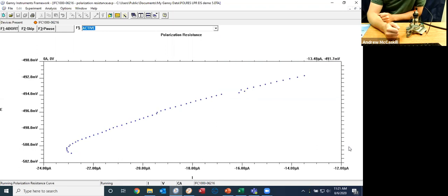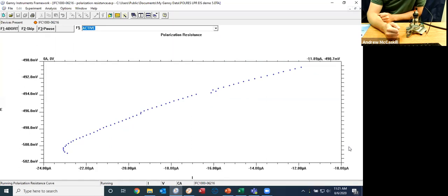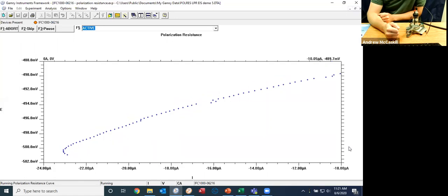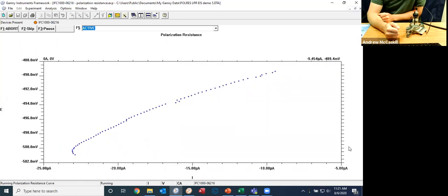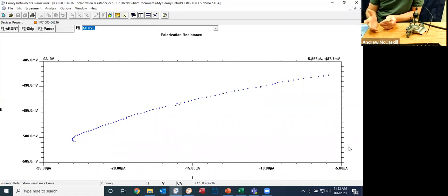Is it necessary? No, it's highly recommended. There are so many variables in this system. To control them all is very, very difficult. So anything you do to help yourself out is probably a good plan. So by using the mask, there's a couple things that you're doing. One, you're defining your surface area to a designated size. So that's going to help you out in your calculations.